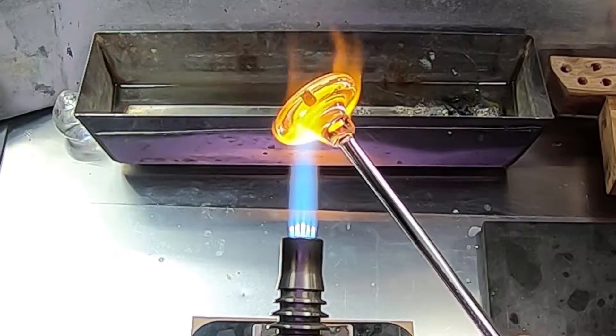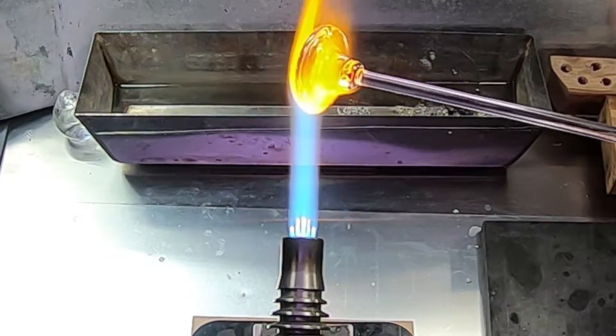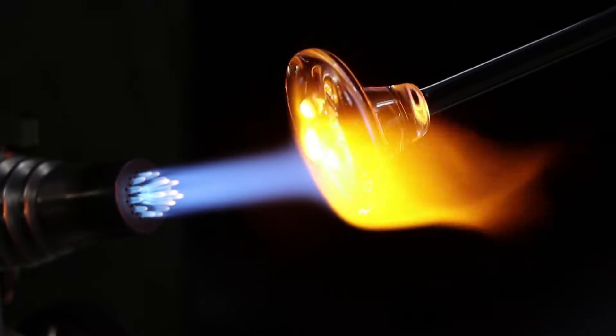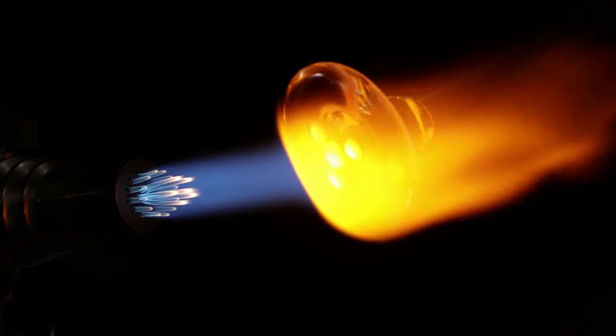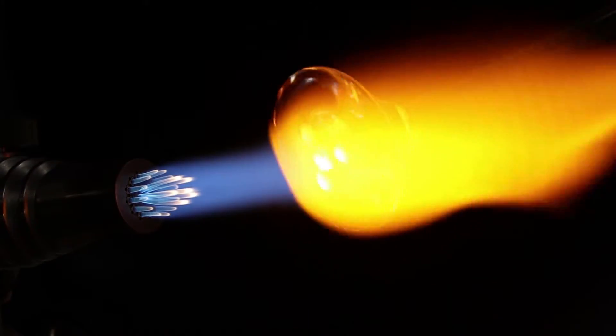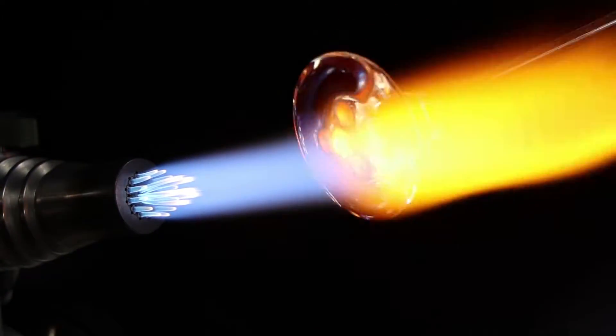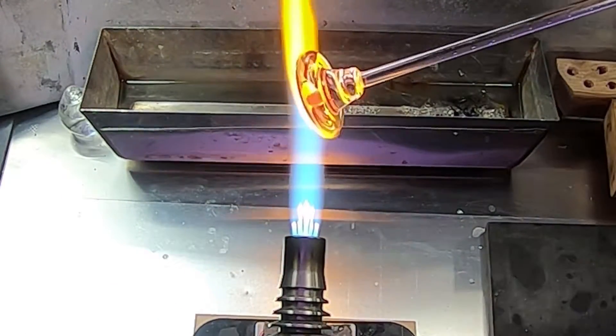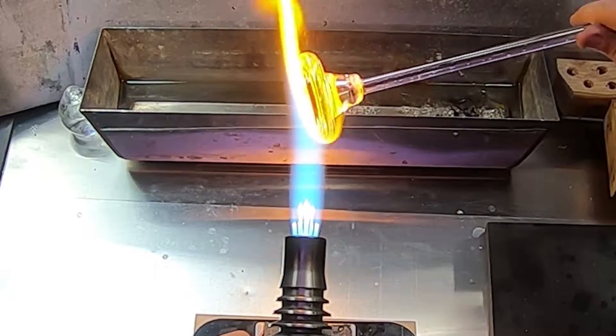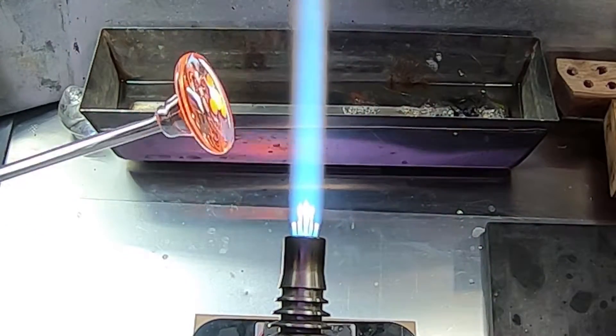To move forward with this implosion marble, I'm going to start to focus my heat on the back of it, kind of push some heat all the way through — just a little bit of base heat, not too much to where I start to destabilize the punty. Then I'll flip it around and start to push a lot of heat into the front, the surface there. The idea is to have that clear glass begin to melt and kind of gather around the dots and begin to implode them in. Ultimately I'll be melting the disc down into a sphere, and it's quite a large disc for such little detail, but I'm really trying to focus on the process here to show you how they suck into it.